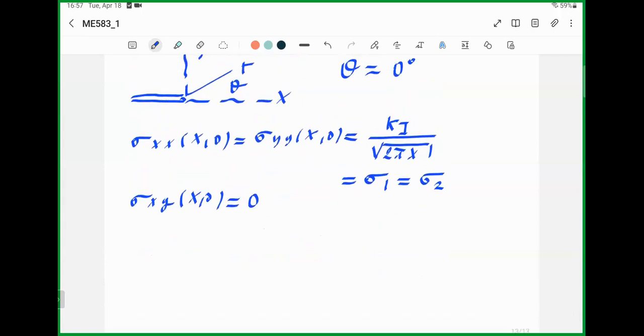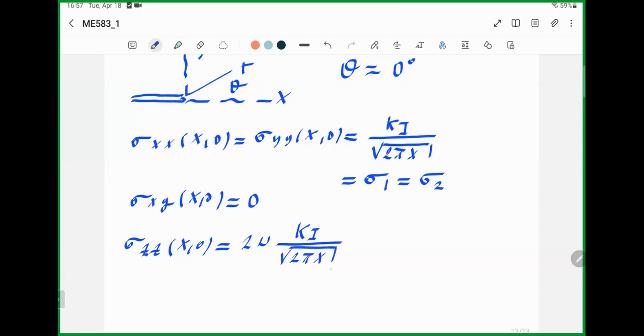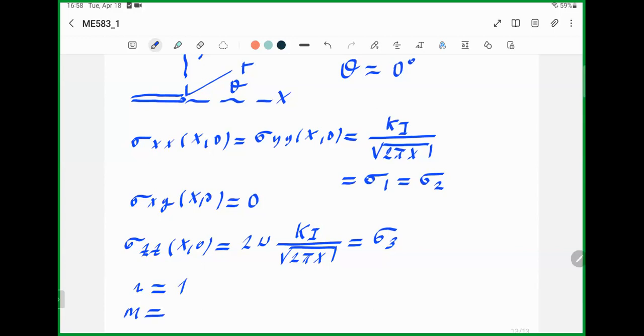But sigma_z is different now — there is a triaxiality in the z-direction. Sigma_z at (x, 0) equals 2ν·K1 over the square root of 2πx. This is taken as sigma_3. Using the von Mises criterion to find the plastic constraint factor: sigma_3 is 2ν times sigma_x plus sigma_y, so n equals 1 and m equals 2ν. This gives the plastic constraint factor for theta equals zero, which depends on ν. Approximating ν as one-third yields a plastic constraint factor of approximately 3.